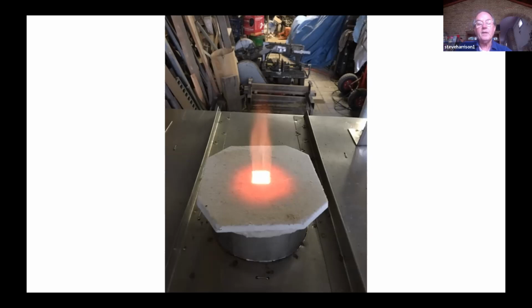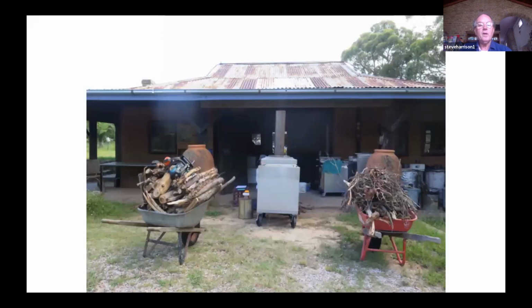off the pressure gauge. That's about as low as my pressure gauge can sensibly read. Any lower than that, and it's not accurate. So it's about the lowest possible setting for pressure, and a very low volume. As I say, 400 grams of gas, more or less. I think there's one more. Okay, no, there isn't. Okay, well, this is now changing to the little portable kilns.